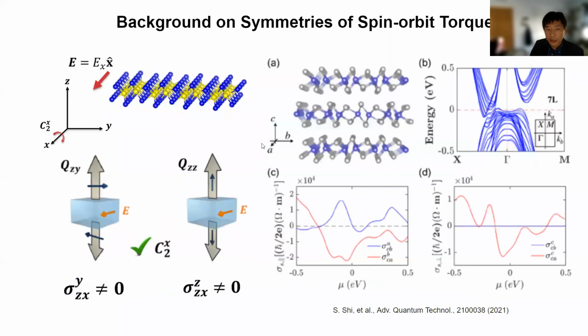So if you perform the same symmetry analysis, what you find is that in this case, this ZZ component is allowed. In other words, you can have a spin current going along Z with a spin component pointing in the Z direction. Recently there has been an experiment that performed this spin orbit torque on this tungsten ditelluride, and indeed they have also observed this component.